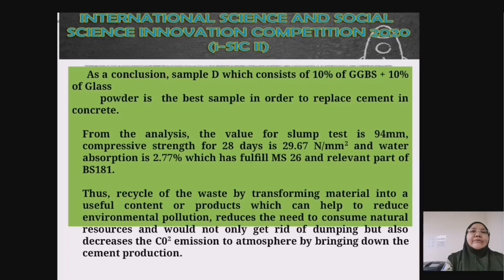As a conclusion, sample D, which consists of 10% of GGBS and 10% of glass powder, is the best sample in order to replace cement in concrete. From the analysis, the value of slump test is 94 mm, compressive strength for 28 days is 29.67 Newton per mm square, and water absorption is 2.77%, which fulfills MS 26 and relevant part of BS 181. Thus, recycling of waste by transforming material into a useful content or product can help to reduce environmental pollution, reduce the need to consume natural resources, and will not only get rid of dumping, but also decrease carbon dioxide emission to atmosphere by bringing down the cement production.